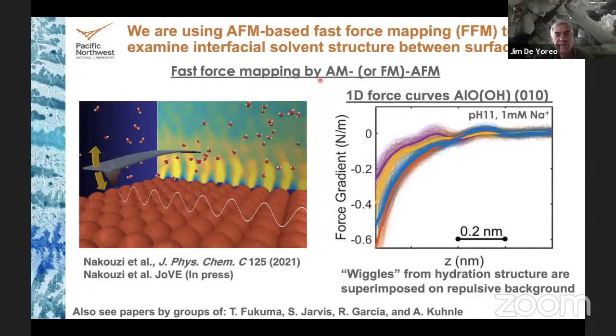Now, the way this works is either an amplitude modulated or frequency modulated mode. The AFM cantilever is oscillated up and down as it moves across the surface, and one measures the shift in frequency or amplitude or phase, or feeds back on amplitude or frequency and measures the voltage needed to keep it constant, and you can measure the phase shift. And the map here is actually a map of the force gradient seen above the surface, but I'll get into that in more detail in a minute.